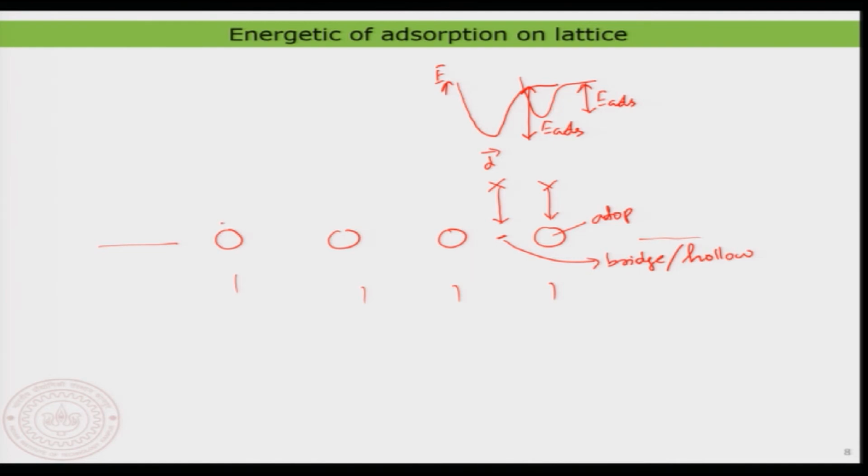you would find that the adsorption energy is low at this point. Let me take a slightly different color to highlight this. On this side I have a very low adsorption energy, and then when I come here I have a high adsorption energy. That means the profile of the adsorption energy would look like this, as periodic as the surface, and this is the typical magnitude of the energy difference between the adsorption energy of a top site, a hollow site, or a bridge site, and so on.